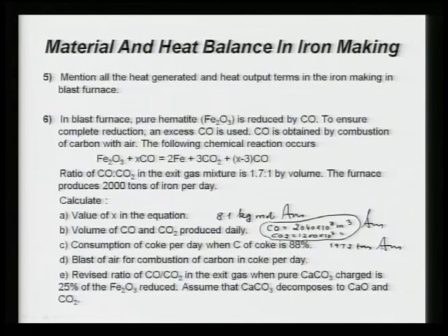Now, blast of air will be equal to 3856 meter cube per mole of iron. This is the answer. Now, the revised ratio of CO to CO2 in the exit gas when CaCO3 is charged: the revised ratio CO upon CO2 will be equal to 1.624. I think the ratio in the original was 1.7:1, now it is 1.624, because you are charging calcium carbonate and it is giving carbon dioxide. So, the 6th problem you do yourself, I have already given the answers.